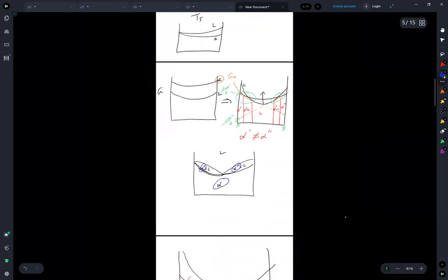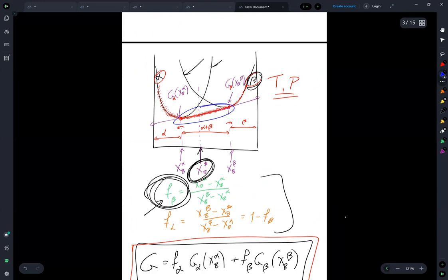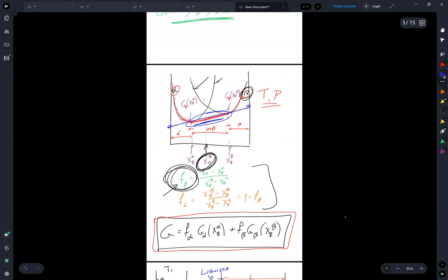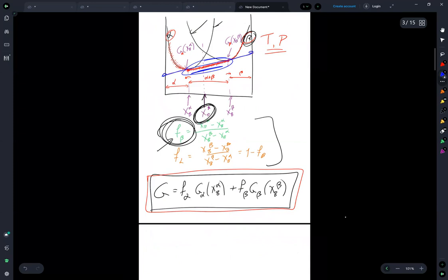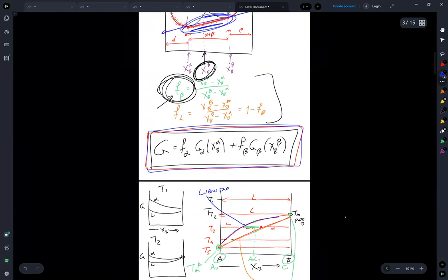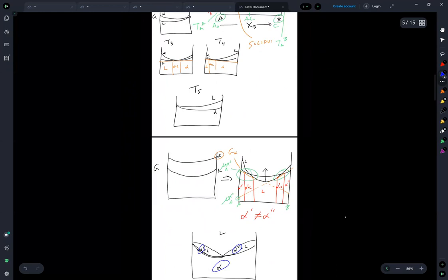As the liquid Gibbs free energy curve rises, these two regions get closer and closer together — the chemical potentials are moving together — right up to the congruent point, where alpha-double-prime and alpha-prime become equivalent and simply become alpha. So in the phase diagram you would specify alpha-double-prime, alpha-prime, and then alpha. This lecture explains the concept of the common tangent line between two phases in a binary system. As we go to higher-order systems, instead of a line it becomes a plane, but the same idea applies — equilibrium requires matching chemical potentials — and we've derived the Gibbs free energy along the tangent line and its consequences for phase diagrams.